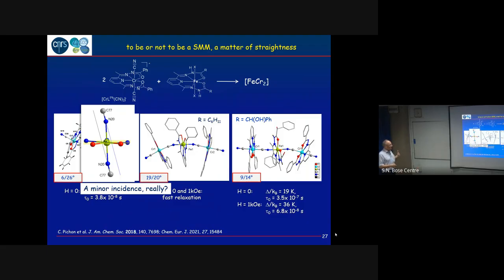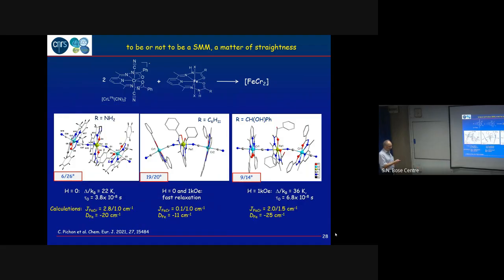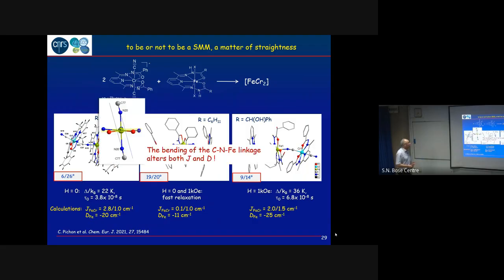to have some insight on that, we made some calculations. Actually, the result is that the angle is important. So here we have very small angles, and what you can see is we have an exchange interaction that is much larger than when there is a strong bending. And the same applies for anisotropy. So in this system, for the iron, the anisotropy is -25, and here we come down to 10. And now we can understand why this is a single molecule magnet and this is not, because we lose exchange interaction and we decrease the magnetic anisotropy.